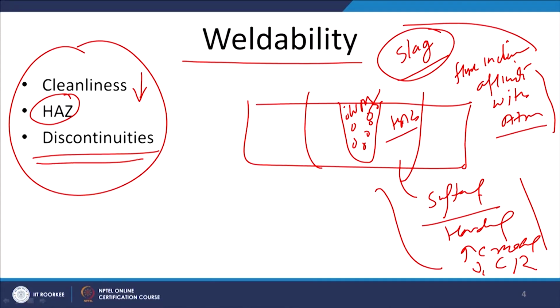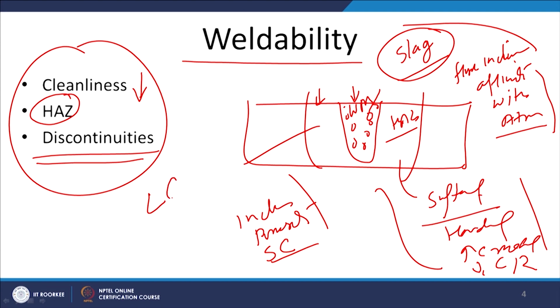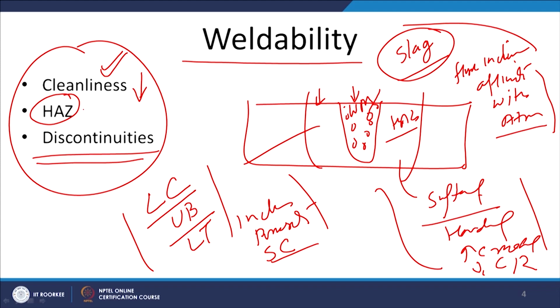Likewise, the weld discontinuities. Weld discontinuities can happen in the heat affected zone as well as in the weld metal. In the weld metal there can be inclusions, porosity, and solidification cracks, while in the heat affected zone there can be liquation cracking, underbead cracking, and lamellar tearing. So, there are various types of cracking which can occur in the weld metal as well as in the heat affected zone, and which can reduce the weldability of the metal. So, for assessing the weldability of the metal you have to see how clean the weld metal is, how the HAZ properties are affected, and the kind of discontinuities formed when a metal is welded, so that we can have a fair idea about the weldability of the metal.